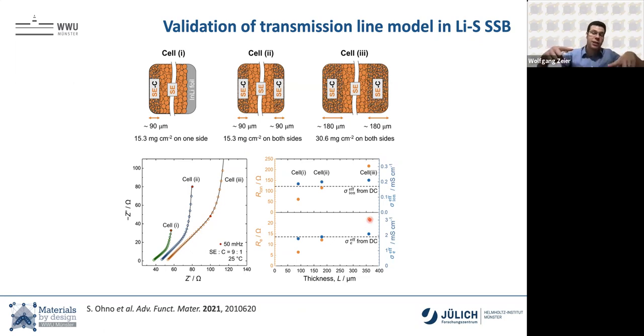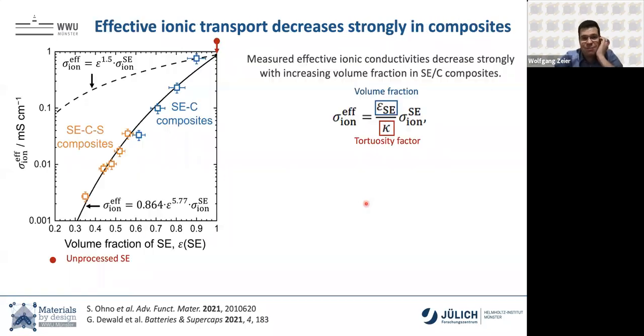And if you back calculate that into ionic conductivity, it actually ends up fairly well where your effective ionic conductivity would be from DC. So the DC are the polarization measurements. All of this here is impedance. So the transmission line model works. Now we can use that to measure the ionic transport in these composites.